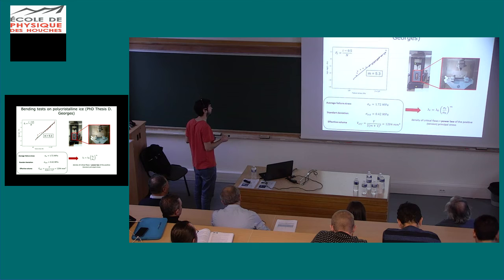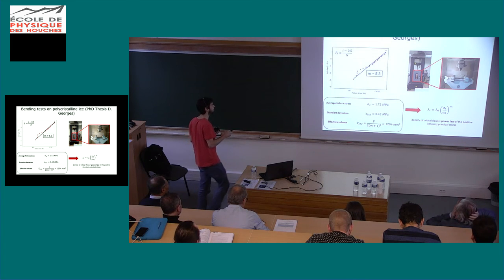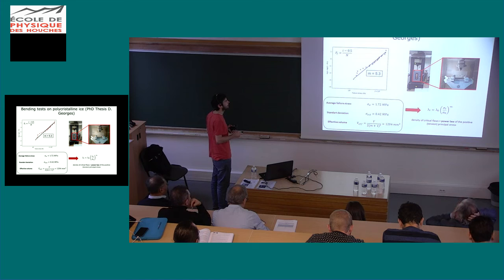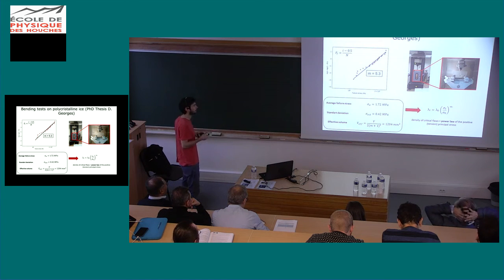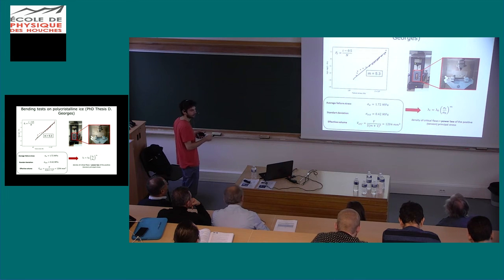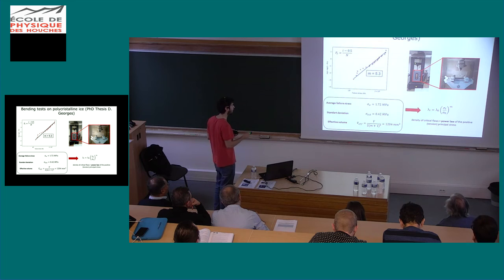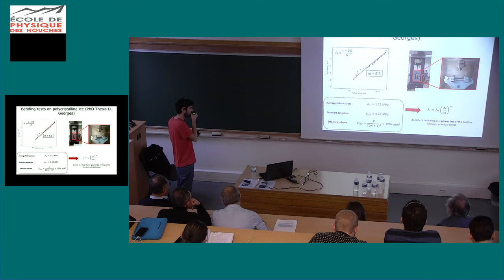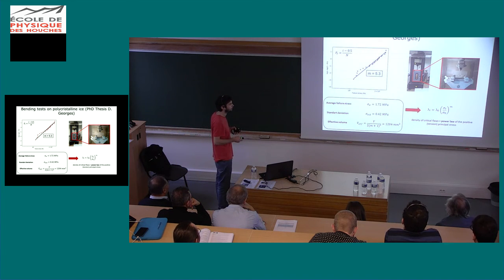Actually, we have a log scale graph of the logarithm of the survival probability as a function of the failure stress of each specimen. And so, as Pascal and Maria said, the Weibull modulus is taken to be the coefficient of the slope fitting the results. The average failure stress of this test was about 1.7 megapascal. And from this average failure stress and the effective volume, we could compute the second Weibull parameter, the scale parameter here.